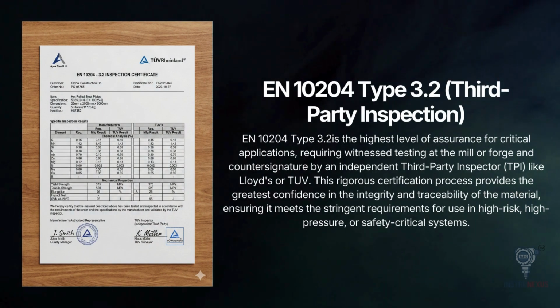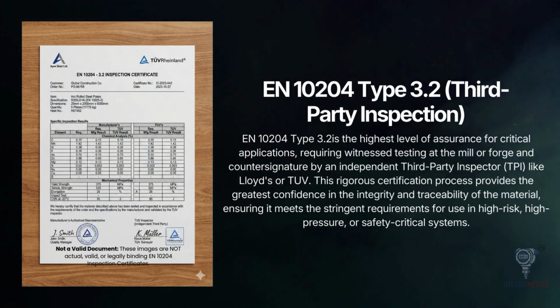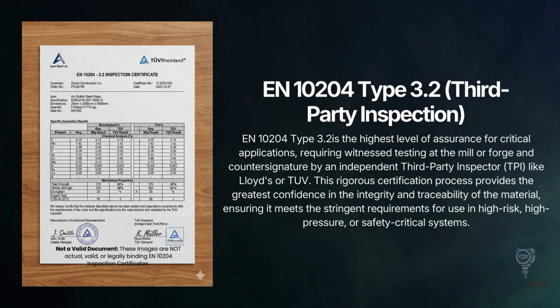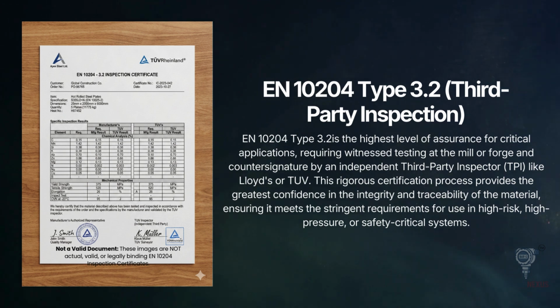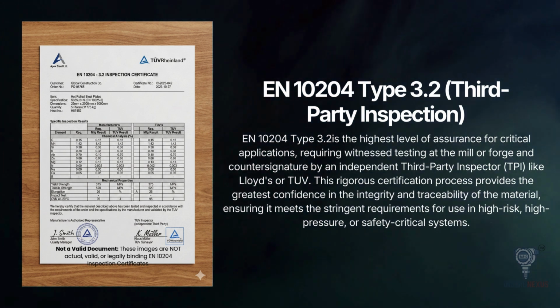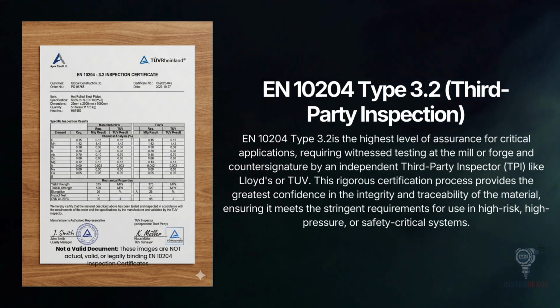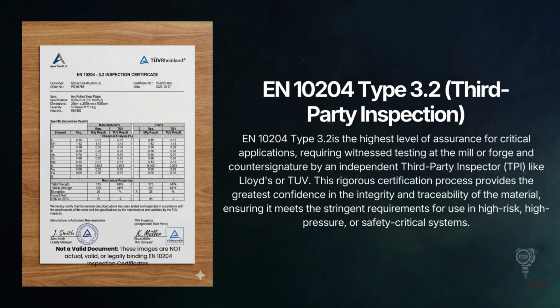At the very top of the pyramid is the EN 10204 Type 3.2. This provides the highest level of assurance for critical applications. It requires everything a 3.1 does, but with an added layer of scrutiny: witness testing at the mill or forge, countersigned by an independent third-party inspector, TPI, like Lloyd's or TUV. This rigorous certification process provides the greatest confidence in the integrity and traceability of the material. You will typically see this requirement triggered for use in high-risk, high-pressure, or safety-critical systems where the cost of failure